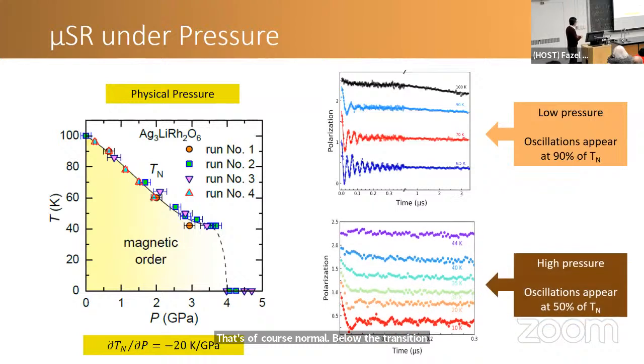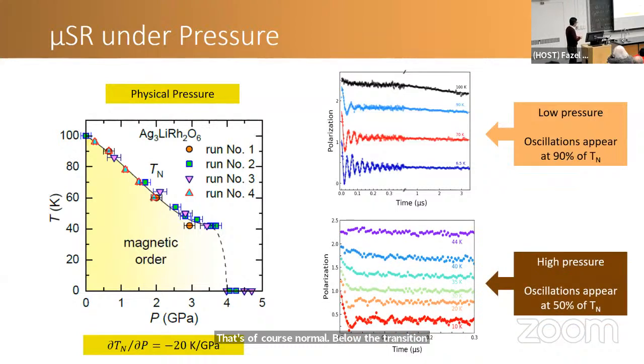However, at high pressures, at 2.5 GPa, we saw a very different behavior. What we saw is that the TN is about 44 or 45 Kelvin, but you have to go to half of that value in order to see the oscillations appear. So there seems to be at least a qualitative difference between the low pressure and high pressure phase. And so it seems that the suppression of the magnetic transition coincides with some serious changes in the magnetic interactions in this material.